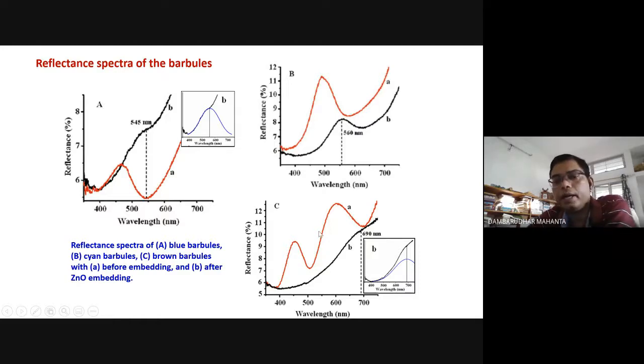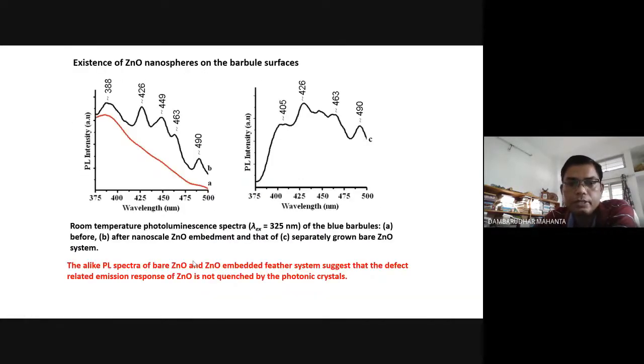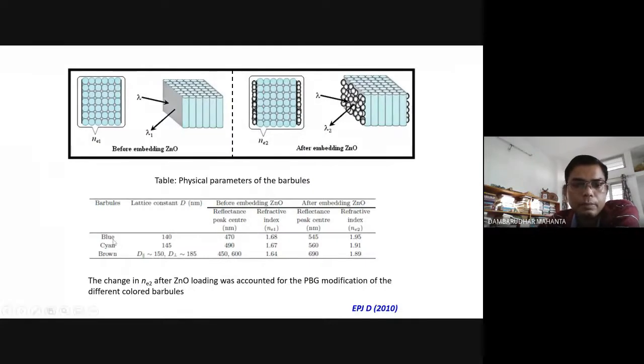Now, the reason behind this brown coloration is that the brown is not giving you a square lattice. In the other two cases, you have a square lattice. In case of blue, you have a square lattice, having lattice constant 140 nanometer or so. For cyan also 145 nanometer. But in case of brown, you have two lattice parameters. One is 150, another in the perpendicular direction is 185. So it's not square. Therefore, you have now two reflectance peak maxima. One is 450, another is 600 or so.